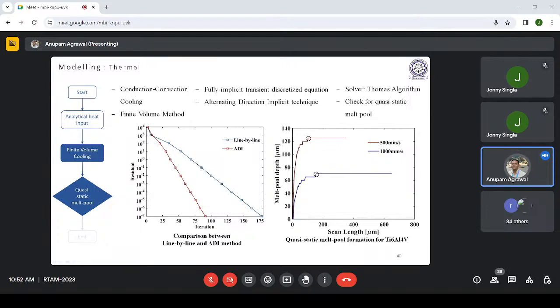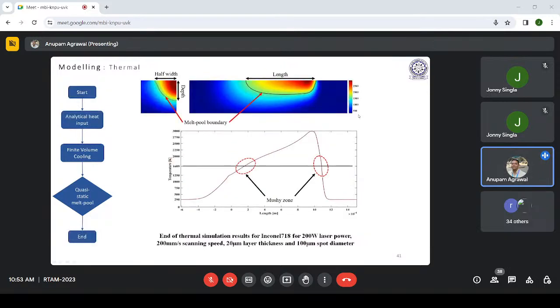So this conduction, convection, cooling, using finite volume method, and alternating direction implicit technique, ADI technique, is used for the comparison of the stabilizing of melt pool, using a Thomas algorithm solver we have made, and the prediction I will show in this slide. We have been able to predict this melt pool geometry, so half width, depth, and from the other view the length of the melt pool, and this melt pool boundary, what it represents.